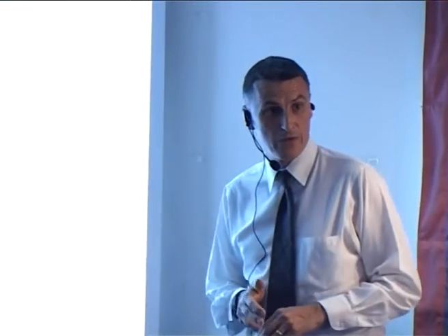For example, say an old jackup comes across from Iran and you have no drawings, no idea what the legs are made out of, but you've got to do a weld repair on it. There may be a PMI — positive material identification — machine nearby. You do the PMI, find out what it's made out of, do the carbon equivalent calculation, and you can get a good feeling for how you're going to weld it up. It's kind of detective work for your welding engineers. The carbon equivalent also shows when preheat is required — the higher the carbon number and the thicker the plate, the more you're going to have to start doing preheat. You'll see this more on offshore projects rather than general ship projects.